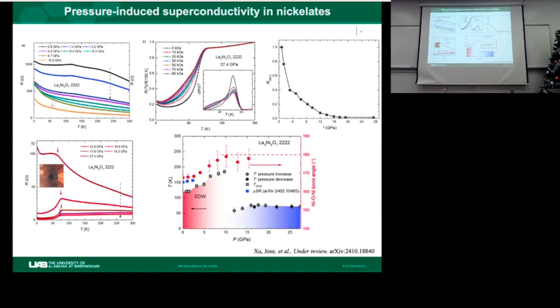And about thin film or bulk, it depends on the detection method. If you want to do X-ray, it depends on the X-ray technique and the energy you want to use. Maybe it could be limited in some cases, if you have a very thin layer of sample and your interaction path is too small. Very often we use a trick, grazing incidence, but in the diamond cell, again, the opening is limited and it can be challenging. But if you do transport measurements, there are still ways to attach the probe on the thin film.